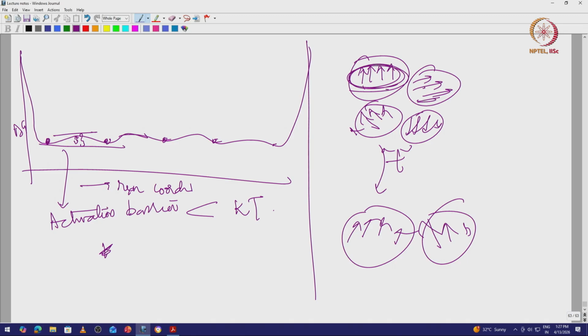As a result, the entropy of this magnetic spin system is not 0. Even if you freeze it down to 0 Kelvin, it can just jump from one state to another state. Now, what does it mean that it's able to show this residual entropy? That means that the number of states that this can take is more, which means that one state can jump to another state by getting over this activation barrier, this activation energy. And this activation energy is set by kT. So the temperature scale for this is kT.